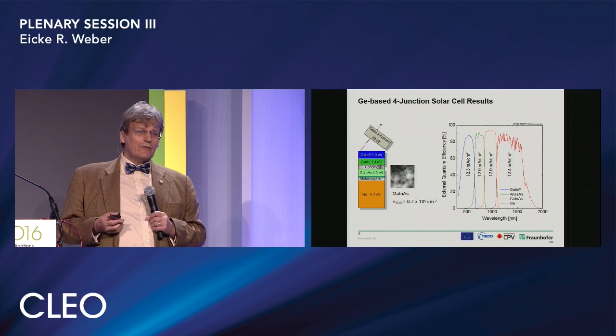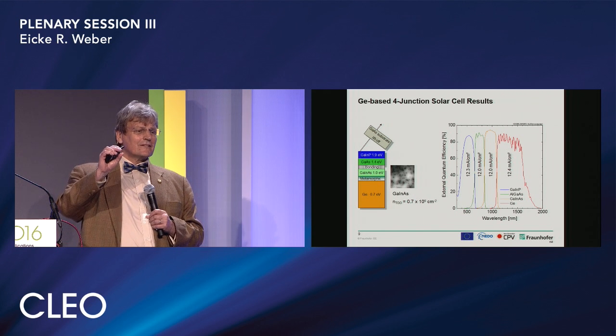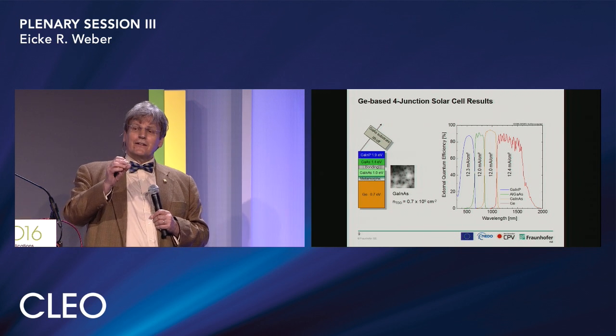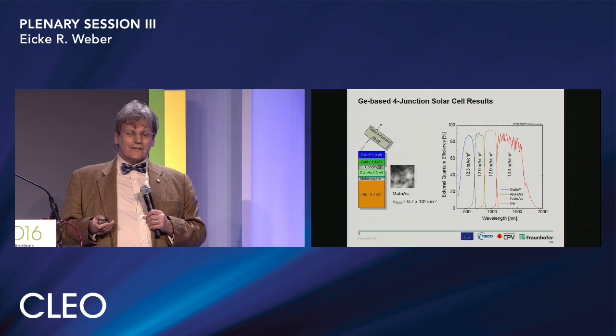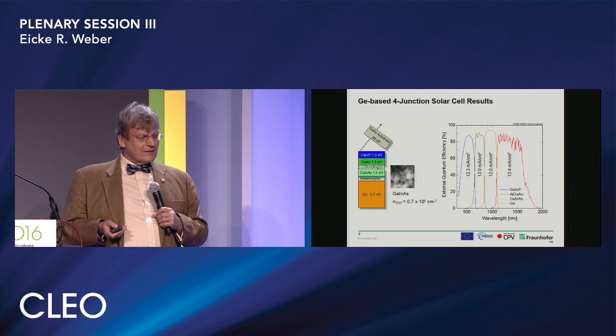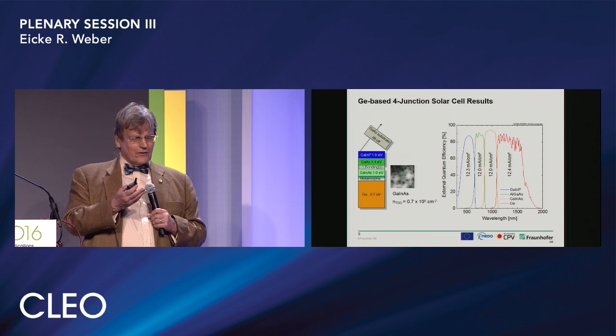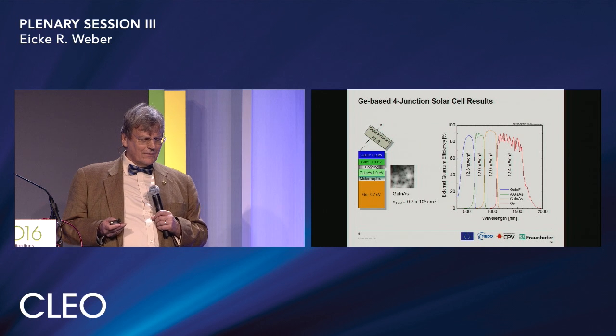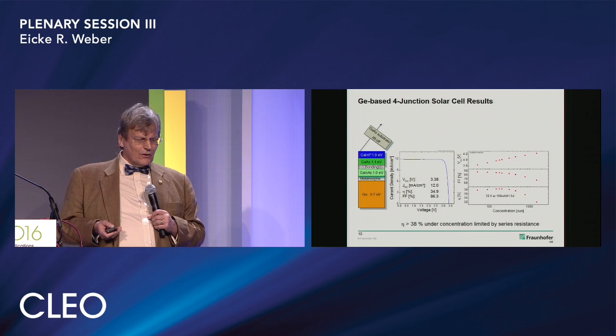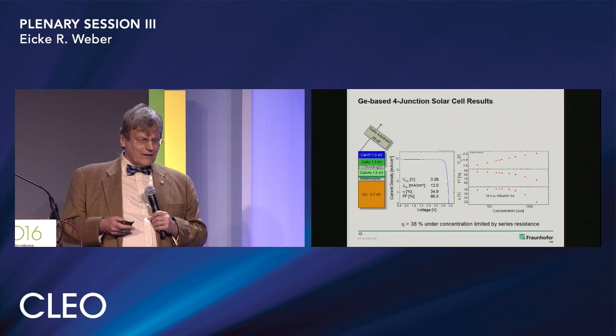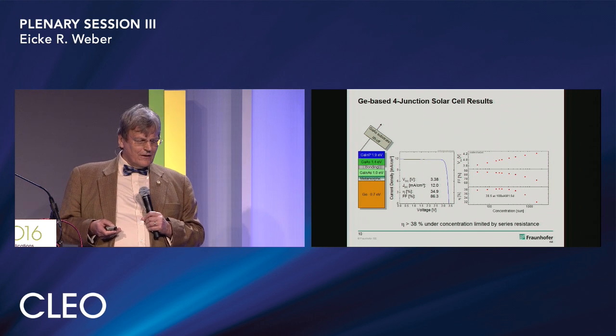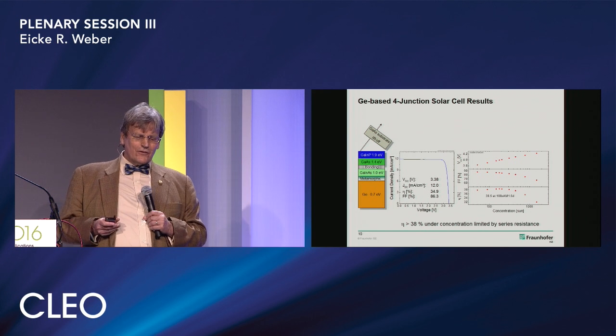Current matching simply involves matching the thickness of the individual layers, because the amount of current created by light depends, of course, directly on the thickness of the layer. And if this is done very diligently, you get a good result as we see it here. And as a matter of fact, with this, one can come already to quite nice efficiency values. You see in the lower picture, 38%. You see the increase with concentration.